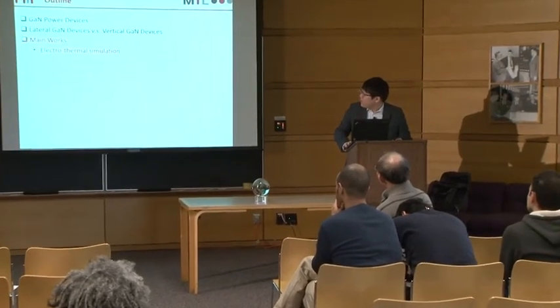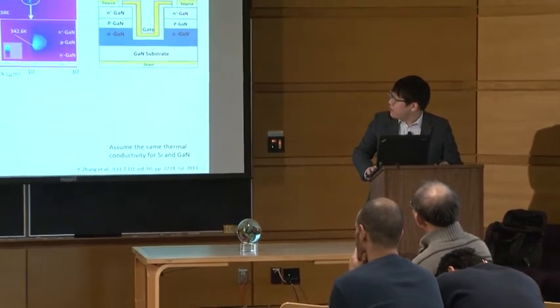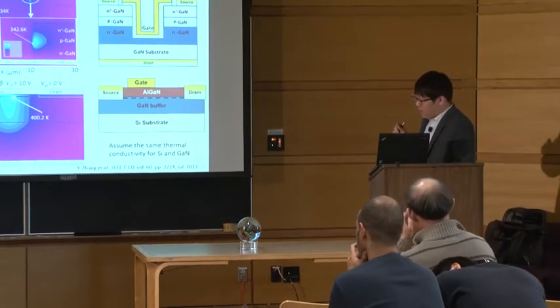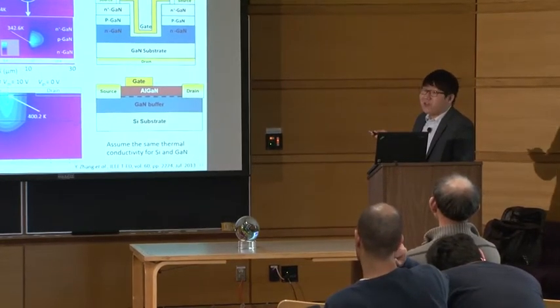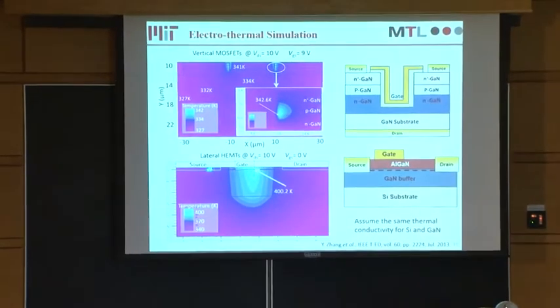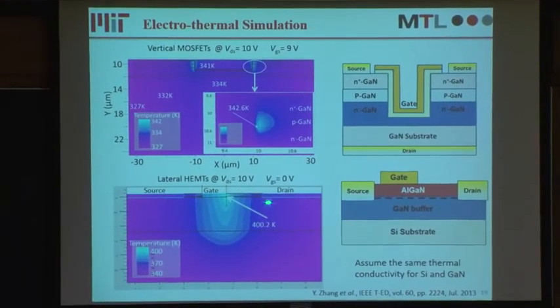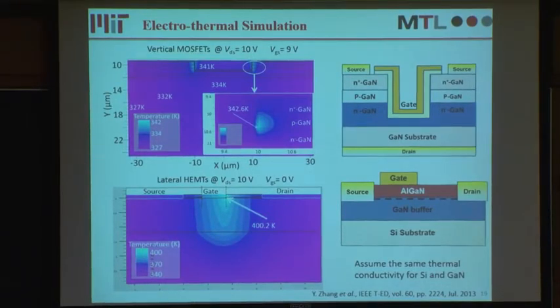I think undoubtedly the vertical device would be better for thermal management. The fundamental intuition is that for the lateral device, the current flows in a lateral direction, so heat generation is in the lateral direction, but heat dissipation is in the vertical direction, since most heat dissipates through the bottom. So the directions are not the same, and the heat generation area is very crowded near the surface. For vertical devices, the direction for heat generation and heat dissipation are actually consistent, so it's more suitable for heat dissipation. Also for packaging, most packages extract heat from the bottom, so it's much easier to extract heat from the vertical device compared to the lateral device.